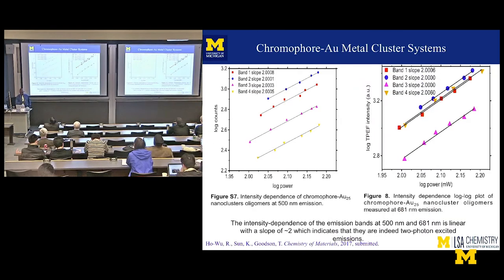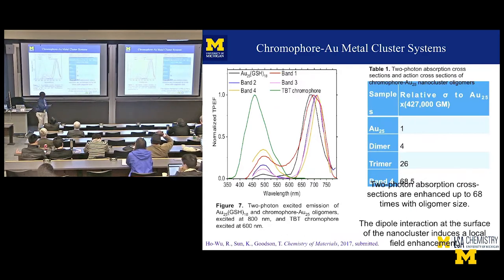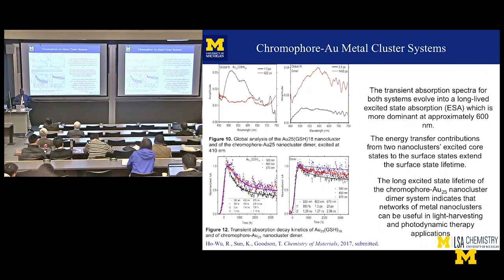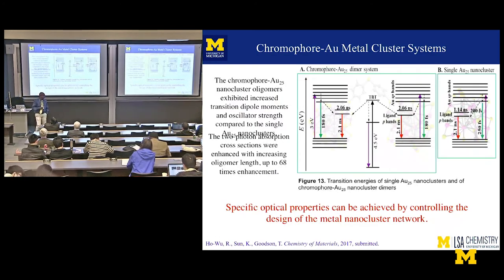Then you can look at the two photon properties, and those two photon values are very large again. This is just showing that you have two photon, but the big point is that the two photon cross-sections are enhanced by 68 times with respect to the oligomer, 68 times bigger, which is also another big result. Then she did the time-resolved spectroscopy, the transient, like we talked about before, on these interesting new oligomer structures to try to conclude what was happening.